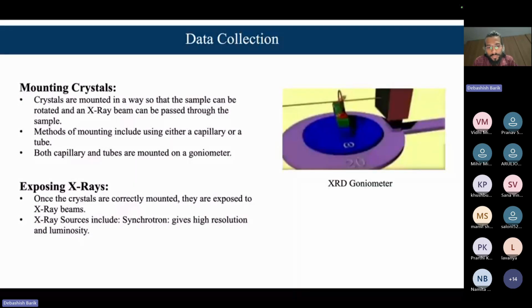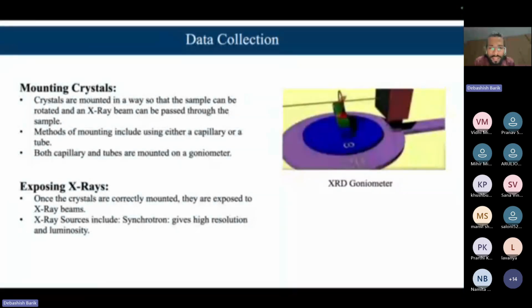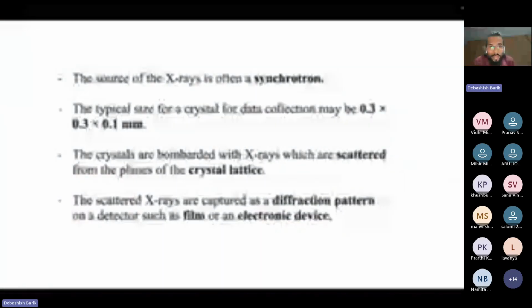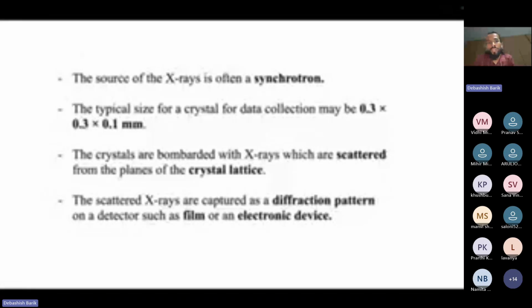Synchrotron is a big facility for X-ray diffraction, and it can give a high resolution structure, nearly 2 angstrom or so. But in an in-house X-ray diffraction facility, we will not get high resolution. So the synchrotron facility helps in getting high resolution data. So the source of the X-rays is often a synchrotron. The typical size of a crystal for data collection may be 0.3 x 0.3 x 0.1 millimeter; these are the dimensions for the crystals.